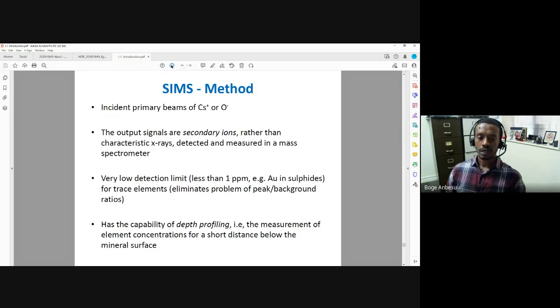And if you were wondering how they work, now in XRD, we say the sample is subjected to X-rays. In SEM, the sample is subjected to an electron beam. In secondary ion mass spectroscopy, the sample is subjected to ions, so cesium ions and so on. So the sample is subjected to a beam of cesium ions, and basically you are fragmenting the sample, okay, breaking the sample literally, and generating molecular products from the sample, okay? And once you break the sample, generate molecular species from the sample, you can use a mass spectrometer to tell you the identity of those fragments. So that's why we say secondary ion is the beam you use, and that's coupled with a mass spectrometer to tell you those fragments belong to gold, the fragments that belong to oxygen, belong to iron, whatever it is.